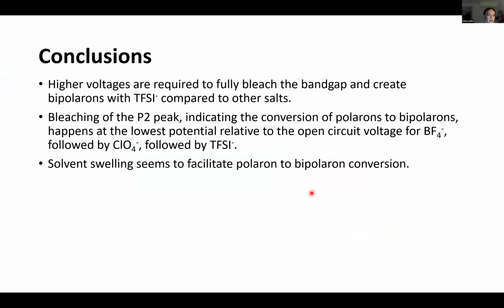So our conclusions from this work are that higher voltages are required to fully bleach the band gap and create bipolarons with TFSI. And we said that was probably because the TFSI is holding polarons at greater distances and preventing them from coupling. Additionally, bleaching of the P2 peak is happening at the lowest potential for the smaller anions. And we also saw that swelling seems to facilitate polaron to bipolaron conversion at these high potentials.